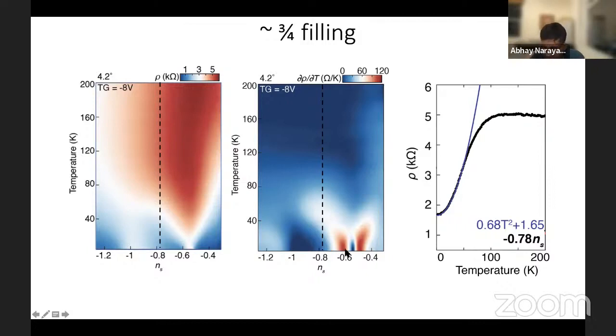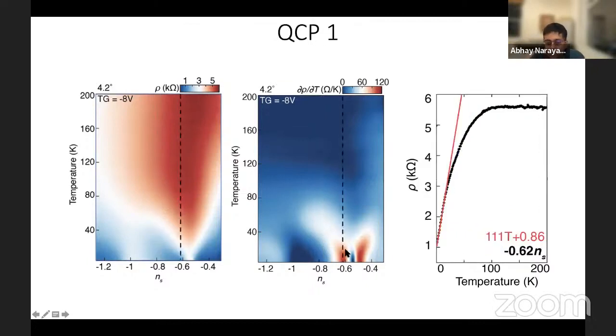And if I come exactly to the metal to insulator transition point, so at the interface, you can see that it's now T-linear, and this linear behavior goes all the way down to the lowest temperature of our measurement, which now is around 50 millikelvin or so.